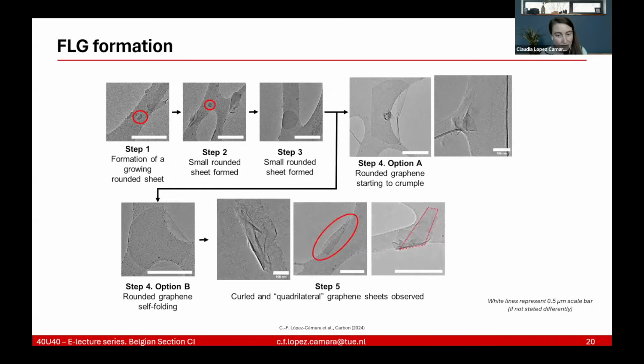Let me see, one second, because yes, there it is. So you can see in this video that it's tilting the sample, so you can see the sample from different angles and it's rolled, as well as in the picture in the middle. So it's a rolled graphene, let's say it's a curled graphene, better said. And then in the third picture, we also see quadrilateral graphene sheets. So if you start folding as if it was a bed sheet, or a paper, you end up with these quadrilateral graphene shapes.